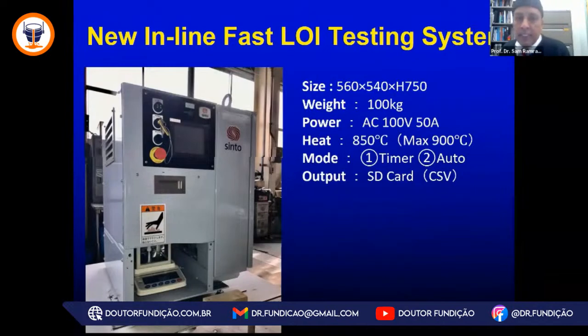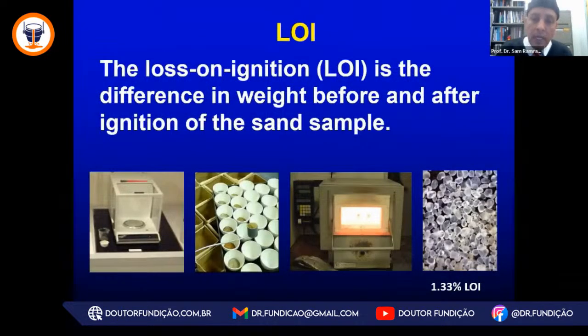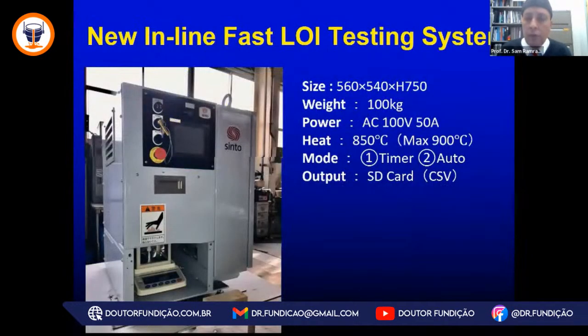Today, we can run this test fast, inline. We can get that loss on ignition data that we would get from the AFS standard test. That test would take at least 3 hours to get the data. It takes 2 hours to run, and by the time we cool down the crucibles and take the change in mass readings, it's about 3 hours before the foundry can use that data to tell if their sand binder systems are high, low, or anywhere in between. Today, we could run this test in less than 10 minutes by using an inline fast LOI testing technology that has been automated.